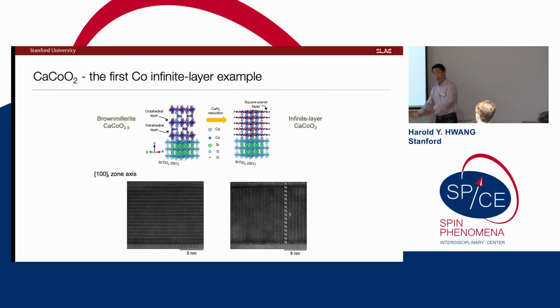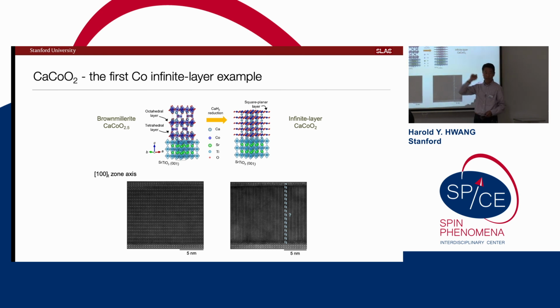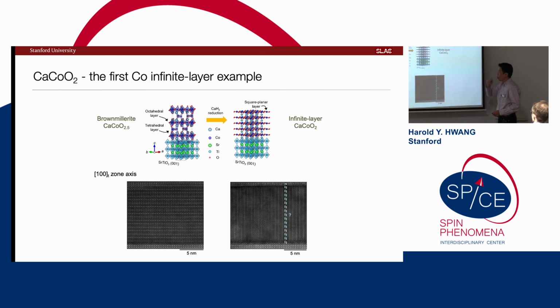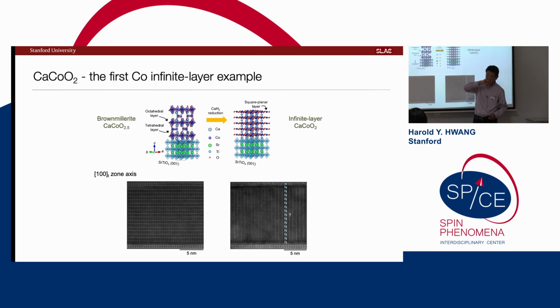So by now I'm going to say you're all experts at this deintercalation chemistry, play similar games. And again, as far as we understand, this is quite a metastable situation. But you can make very nicely, actually, an infinite layer lattice of cobalt O2 planes. Right? So maybe hard to see. This is the so-called Brown-Millerite structure. If any of you play with or know like battery or electrochemistry people, this is quite an important class of materials for them. So we can make a nice crystal thin film of this guy and pull out oxygen.